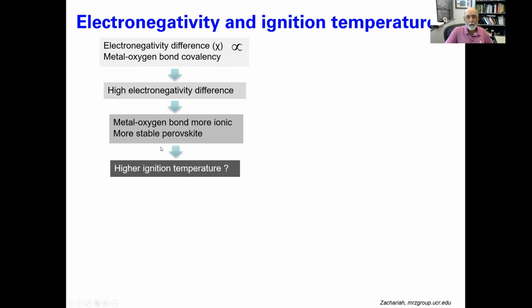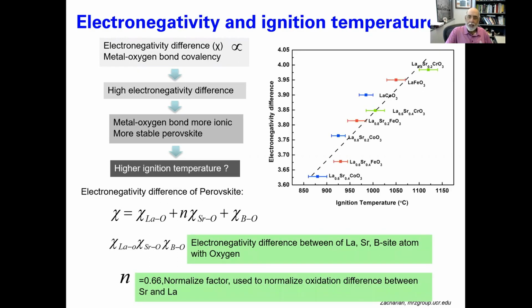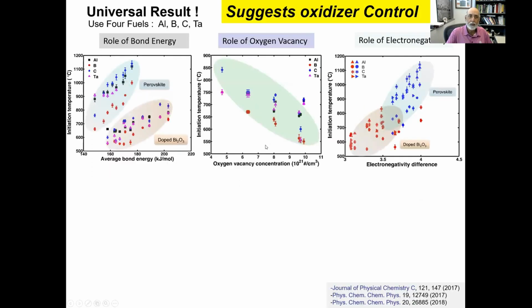So if it's more stable, one would expect a higher ignition temperature. And we can compute the electronegativity in a perovskite. Again, that's been worked out by others, how to calculate perovskites. And now I plot that. And again, we see a very strong correspondence between the ignition temperature and the electronegativity. In other words, the more ionic I make the oxide, the higher the ignition temperature. So the ionic character of this structure can be used to tune the ignition behavior of systems. So again, we can relate to a fundamental parameter, a microscopic parameter of the material.